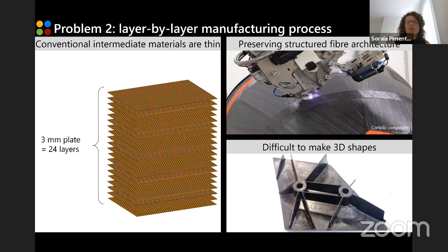Those sheets can usually be down to 1/8 of a millimeter, meaning that if you want to make a plate 3 millimeters thick, which is a normal thickness for a thin structure, you actually need to lay up 24 layers of these composites, and that obviously takes time. Now, there is also the fact that we want to preserve the architecture of the fibers, and that again means that we need to place those fibers and those materials exactly where we want them. And altogether, this makes it very difficult to make 3D shapes with complex geometries.